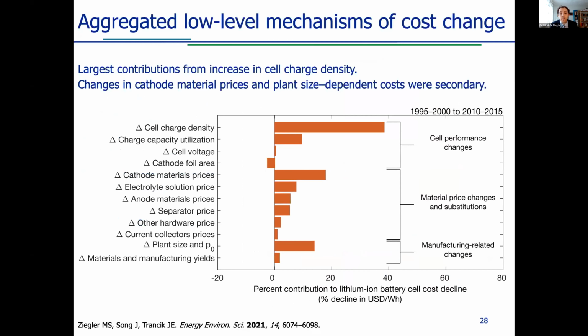We find that the largest contribution to cost change between the late 1990s and early 2010s was the increase in cell charge density, which contributed 38% of the cost reduction observed. The next largest contribution came from the decrease in the price of the cathode material, which contributed 18%. The third largest contribution came from the increase in plant size and the decrease in plant size associated costs, which contributed 14%. We also see significant contributions from a variety of different components, including the prices of the anode, the electrolyte, and the separator.